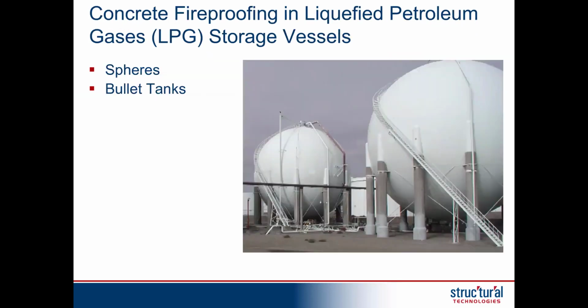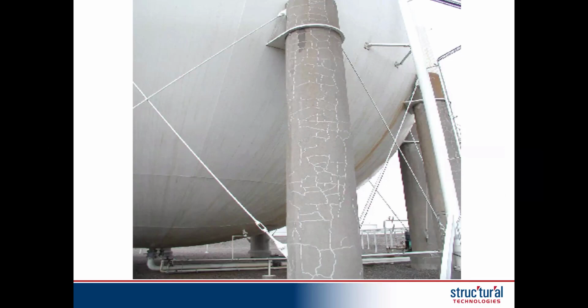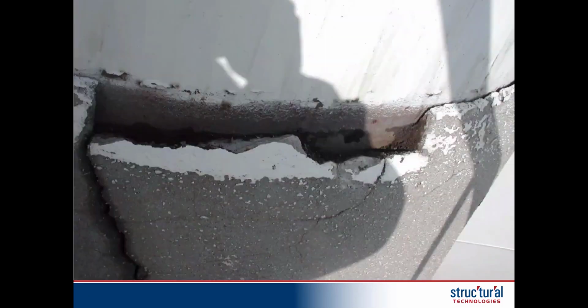So a lot of fireproofing is also on some kind of unique geometric structures such as spheres, and primarily the pipe columns that are tangentially welded to the spheres. And you can see here's a customer who took a painstaking amount of time to seal all the cracking. Probably would have been a lot better to just put an elastomeric coating over top of it to protect it. But when we got to the top of this type of pipe column, we found that they had originally removed the rain gutter, and you can see that from the weld parts, the stitch welding remnants there. And so water was coming right off the sphere and then down on the leg and then going right into that annulus between the cementitious materials that had been tapered and then running straight down the leg and causing corrosion.